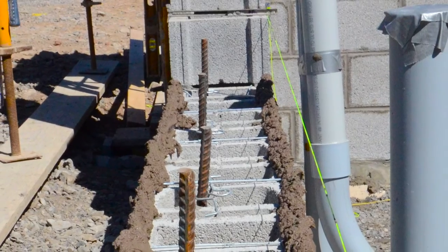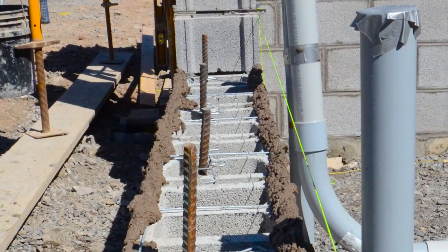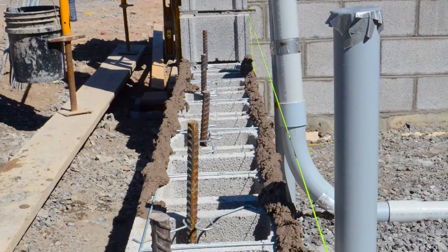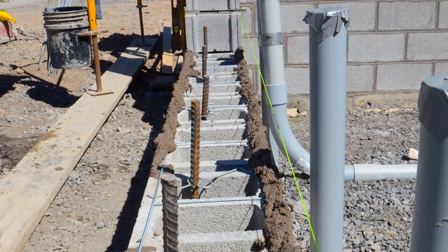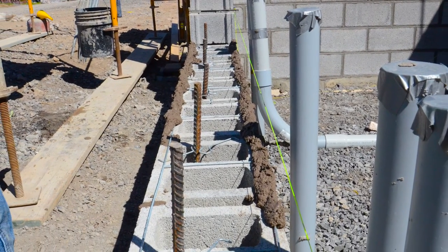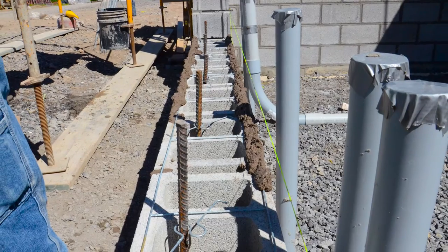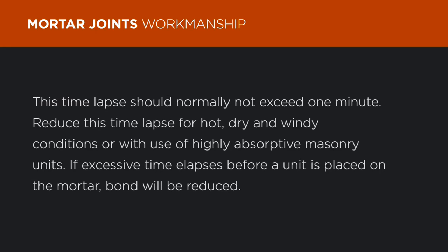Workmanship has a substantial effect on strength and bond. The time lapse between spreading mortar and placing masonry units should be kept to a minimum because the flow will be reduced through suction of the unit on which it is placed. This time lapse should normally not exceed 1 minute. Reduce this time lapse for hot, dry, and windy conditions or with the use of highly absorptive masonry units. If excessive time elapses before a unit is placed on the mortar, bond will be reduced.